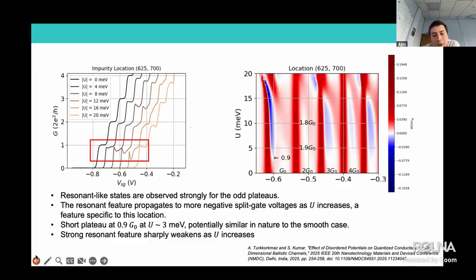Another important thing to mention here, I think an interesting thing, is that we see a plateau-like shoulder at 0.9 here. So in one of these cases, we see a 0.9-like shoulder, then it transitions into a normal plateau that happens at 3 milli-electron volts.